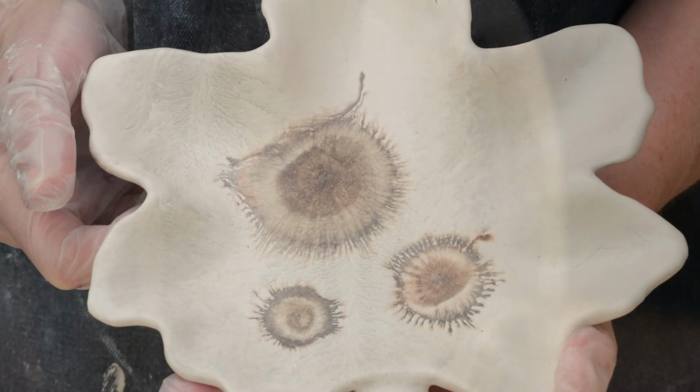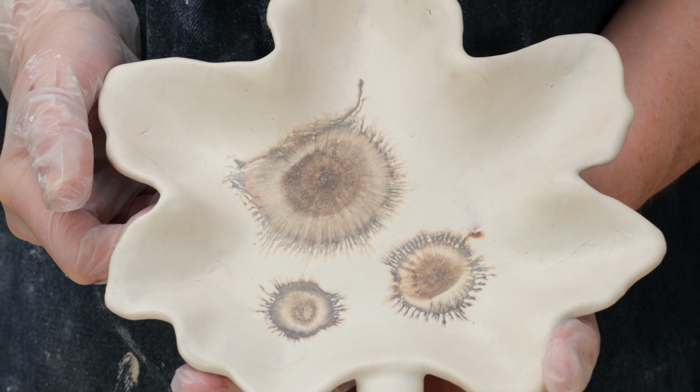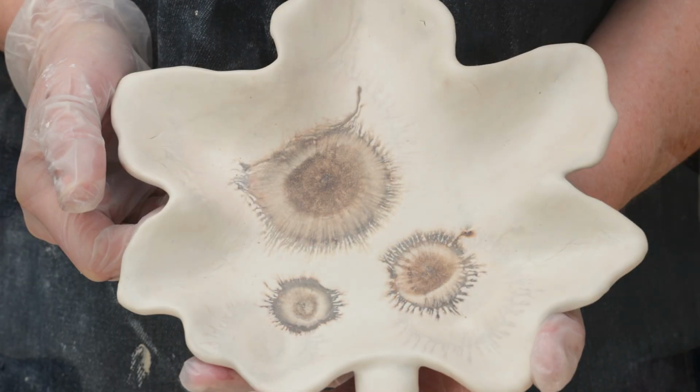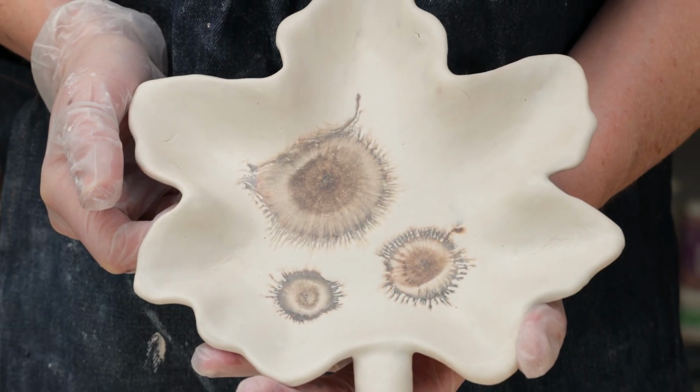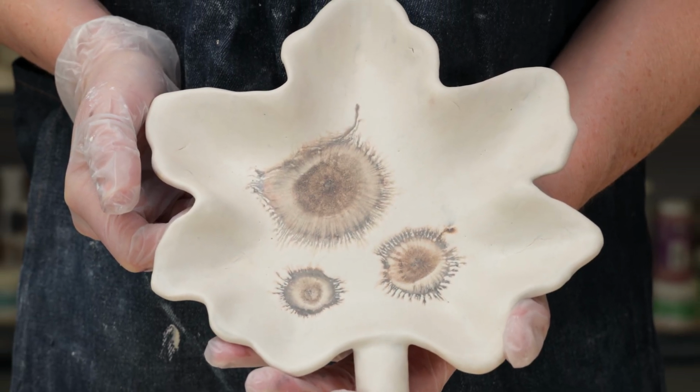Earlier, I made a few more pieces and glazed and fired them. This one I experimented on a leaf-shaped piece. I added a little blackberry wine mason stain to the black for the tea. I used an eggshell wash around the mocha spots and fired it to cone 5 for this look.